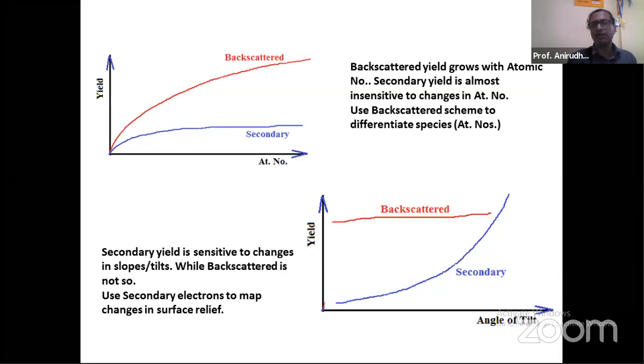Where do you find A? Where do you find B? We will see how we do that. Whereas if you see the secondary yield, that means the flux of the secondary electrons which are emanating from the surface, they are found to be sensitive to the surface undulations or changes in slopes of the surface. So if you plot the secondary yield against the angle of tilt from the surface, you will see that the secondary yield is largely dependent on angles of tilt or surface relief, while the backscattered is not so dependent. So therefore, you can use the secondary electron information to differentiate between differences in surface reliefs, that means differences in distribution on the surfaces, their geometrical differences in their relief.